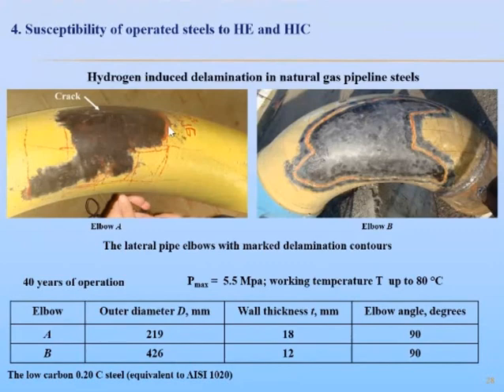Formation of the crack occurred as a result of the pressure of recombined hydrogen being accumulated in the delamination.